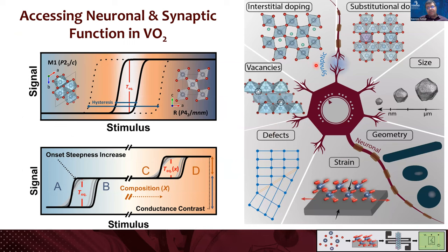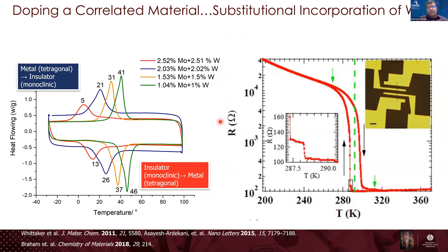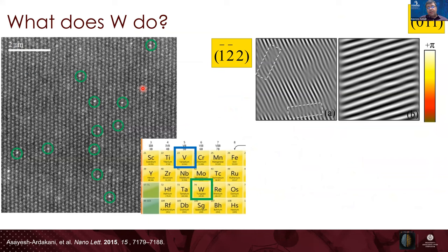And so I'm going to just summarize some of the findings, but this is a beautiful picture that David Santos and my group put together, where you can see a lot of different knobs that we have for tuning the transformation characteristics. And this allows us to start putting together a set of design rules. And one of the things you can do is, of course, introduce a dopant, like tungsten or molybdenum, and that suppresses the phase transformation down.